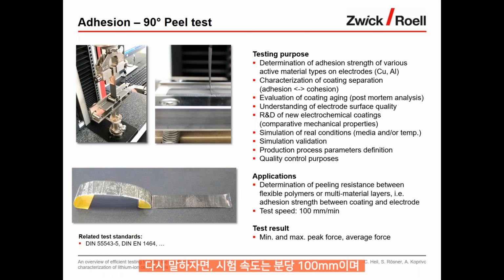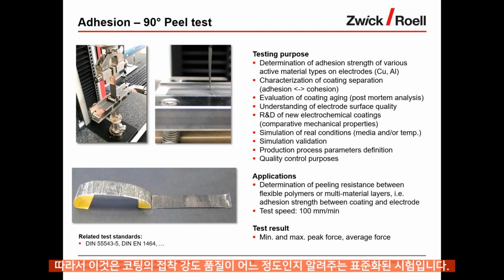So again, test speed about 100 millimeters per minute. The minimum, maximum, peak force is being looked at, and also the average force is being determined. So a fairly standardized test, giving some indication of the adhesion strength quality of the coating.